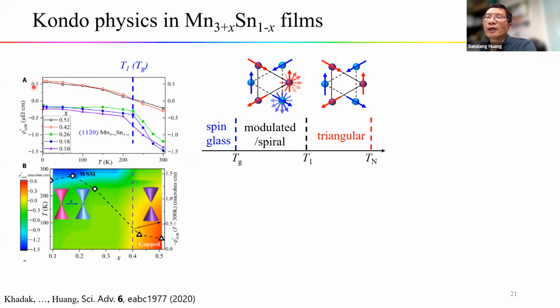If we summarize this figure in this contour map, the color represents the anomalous Hall resistivity, the y-axis is the temperature, and the x-axis is the composition. We can see the state probably happens along this composition and temperature range here. Below this temperature, we may have a spiral structure or possibly a spin glass state. In this range, we have the Kondo gap state. This is the result for the (1120) films.